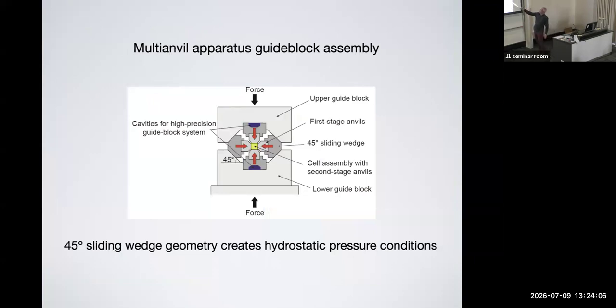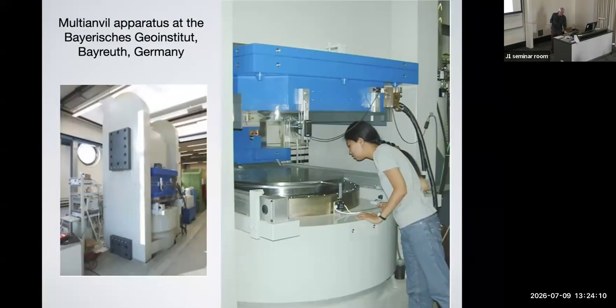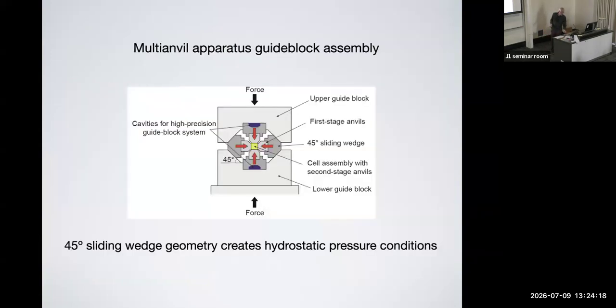So this is the guide block assembly, right? So this part here is essentially what is slid in here. You can see that that's where the guide block assembly goes. This is what contains your actual assembly here. And the advance with this particular multi-anvil apparatus was that you have this 45-degree sliding wedge geometry so that you create a near hydrostatic pressure on your sample, right? That's the key for grain growth. You want to have hydrostatic conditions. You don't want to do a deformation experiment. So during deformation, you reduce the grain size because you put energy into the grain. Here, we wanted to look at just grain growth without deformation. And so that hydrostatic environment is key to conducting the experiments. And the cell assembly here, I'll show more pictures of that, sits in the center, it's compressed here.